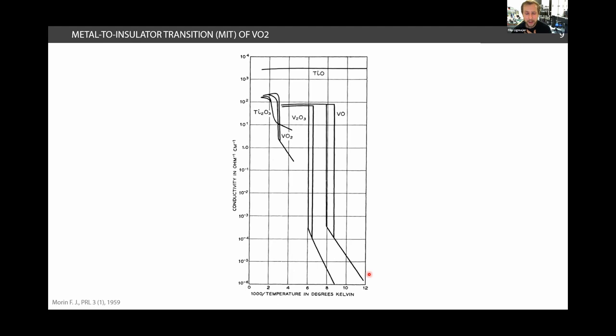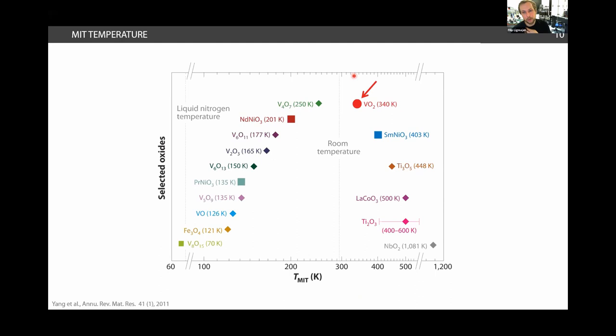Why in particular this VO2 stoichiometry is one of the most popular today is because the transition temperature of VO2 is probably the closest one to room temperature. So it's around 68 or 70 degrees Celsius, quite easily achievable. You don't need a very expensive cryostat or heating to very large temperatures. This is achievable very easily and you can even push this transition temperature down closer to room temperature by doping. So VO2 seems to be very promising in this aspect.